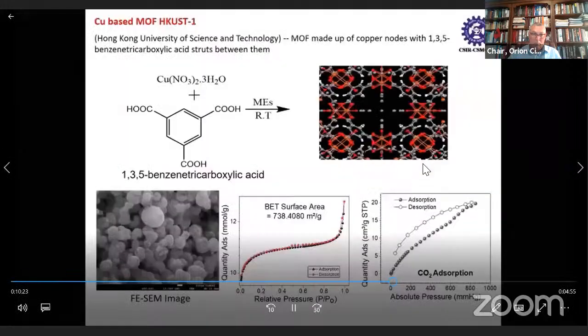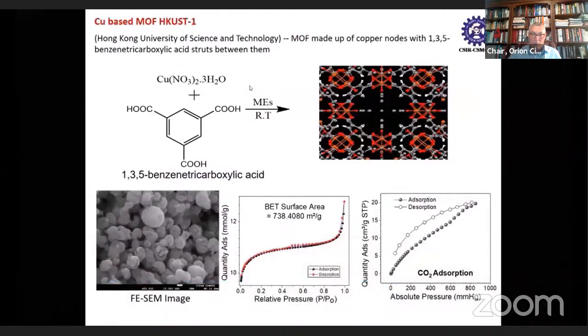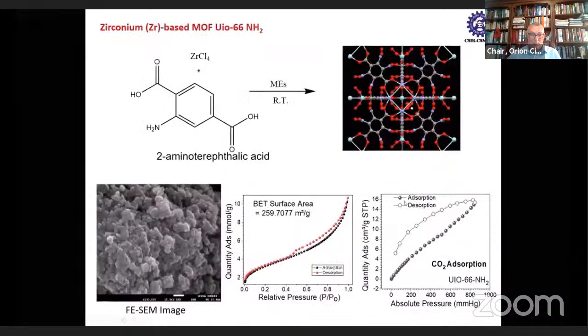These microemulsion droplets were used to synthesize different types of metal organic frameworks. Initially, we synthesized copper-based MOF, HKUST, using copper nitrate and benzene tricarboxylic acid precursors. They were mixed in microemulsion systems, and at room temperature, we got MOF with spherical morphology, which were characterized for surface area and CO2 adsorption properties.